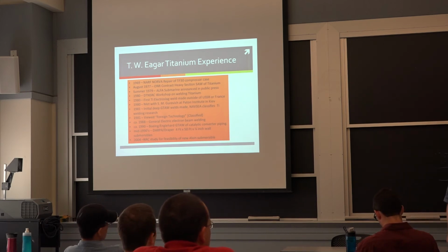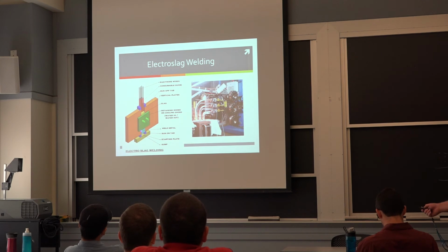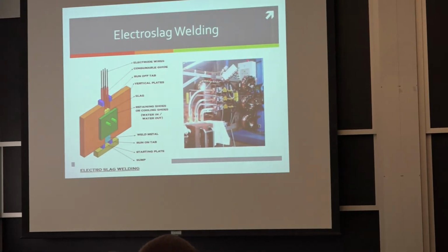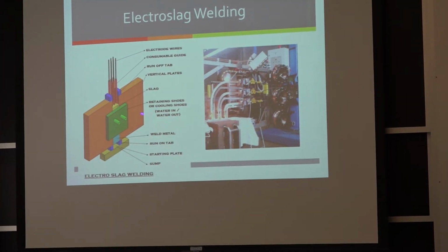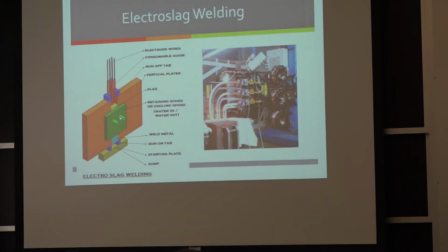I might as well show you the next slide, which is a picture of electroslag welding, which is different than submerged arc welding. Basically you have two vertical plates, water-cooled copper shoes, a base starter tab. You feed electrodes in, and you're only going to use a few ounces of flux. The flux is just a resistive heating element, and you melt the electrodes, and it makes the weld very quickly. We put down a 2-foot high weld in about 5 or 6 minutes. That's why it's such a fast weld. But in titanium, it turns out to be a very efficient process.